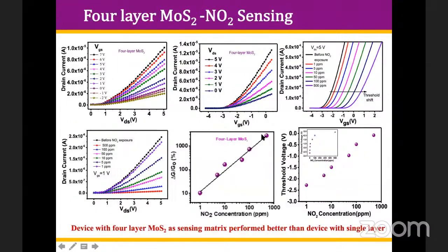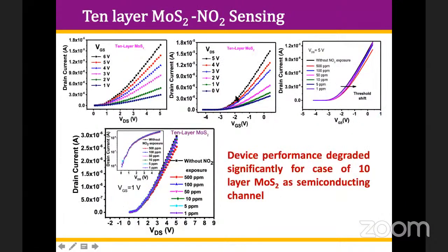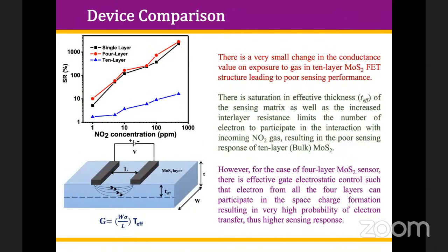Similar characteristics have been studied with 4 layers of MoS2, and with 4 layers of MoS2, the response was found to be much better as compared to the single layer. We also tried with 10 layers of MoS2, but the response was degraded. So ultimately what we found is that 4 layers of MoS2 give a much better response as compared to your conventional 10 layers or monolayer of MoS2.